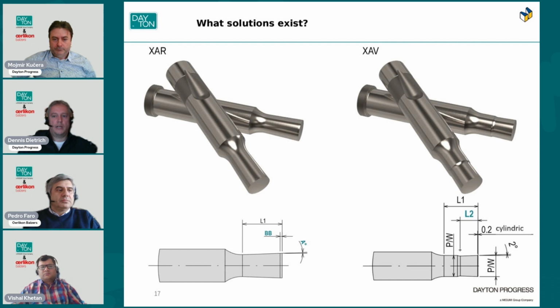Punches with a relief grinding are the most commonly used and probably the best variant to prevent punch galling, because here the friction between the punch and aluminium is dramatically reduced. We see the XAR alteration on the left. The angle and the length are freely configurable, and the angle A is limited to 10 degrees.